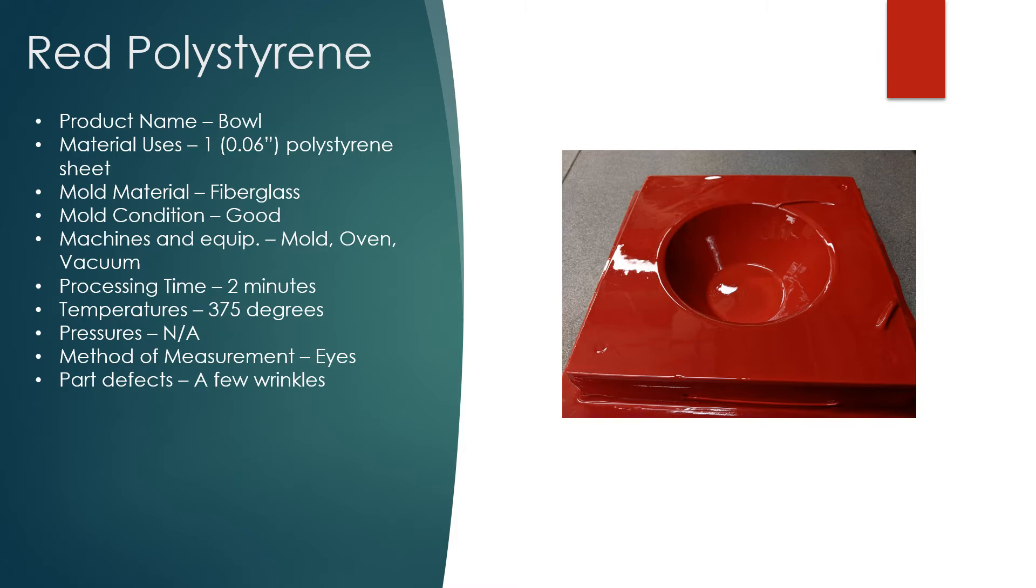The temperature wasn't adjusted from the white polystyrene, so it was still at 375 degrees. No pressure was mentioned. The method of measurement here is eyes and looking to see when the plastic starts to droop down a little bit to tell when it's hot.